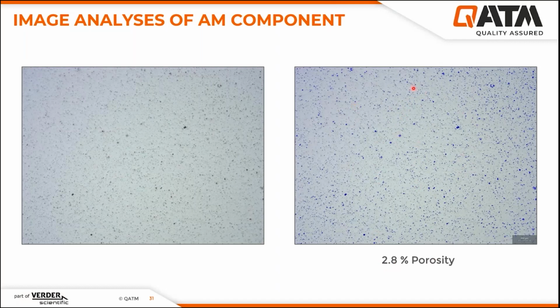Here, to measure the porosity percent, it is very important to not smear the material on the pores, to not cover and close the pores. And here the right metallographic preparation is very important.